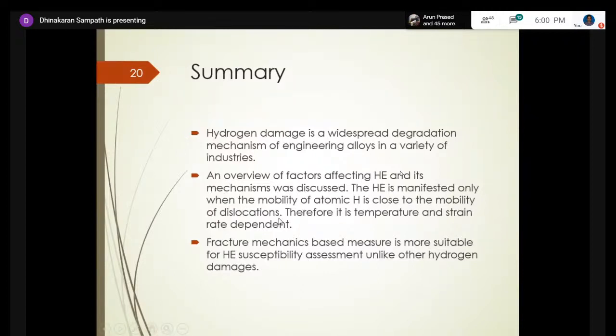The mechanism and the factors affecting hydrogen embrittlement. One key important thing to remember is that hydrogen embrittlement occurs when the mobility of the hydrogen is very close to the mobility of dislocations. If the hydrogen is not moving with the dislocations, it's not going to create any kind of problem, because when a dislocation moves and hits an obstruction at high velocity in the presence of hydrogen, it's going to create stresses. If they are not coupled, the effects are minimal. Therefore it is dependent on temperature and strain rate. That's the key to remember.